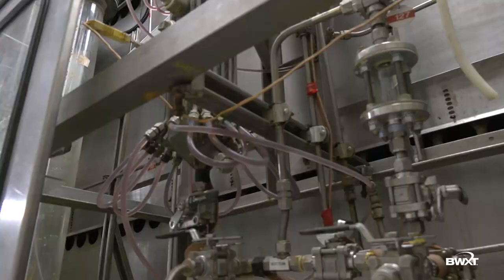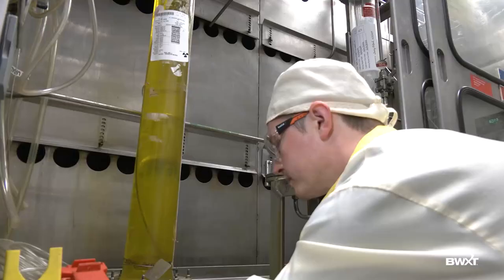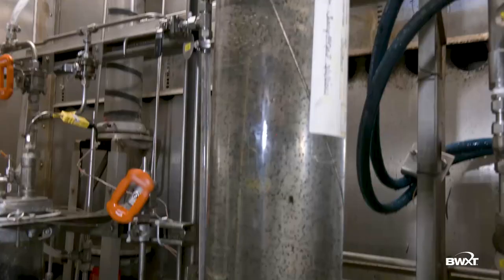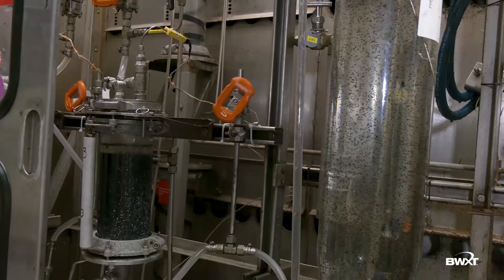Our Triso production process begins with solution preparation, where feedstock of any enrichment is dissolved in nitric acid. The feedstock batches are then blended to obtain the correct enrichment. Blended uranium and proprietary organic solutions are mixed and added to the forming station, maintaining specific temperatures to inhibit the gelling of the liquid. The solution is forced through an orifice to form spherical particles that are then hydraulically transported from the forming column to the collection vessels.